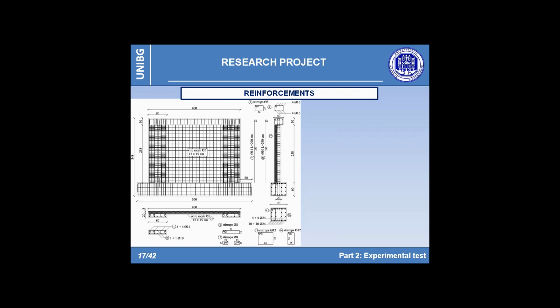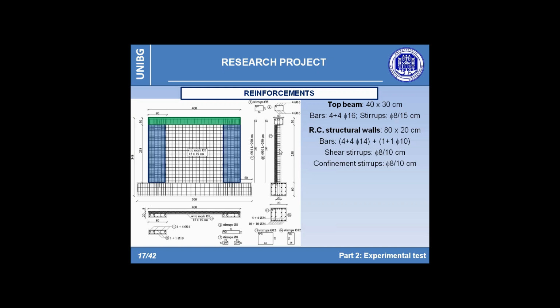In this picture, that is the last regarding the experimental campaign, the specimen geometry and the reinforcement details are shown. As you can see, the spacing of the bars and of the stirrups is very repetitive, highlighting a regular layout. In particular, you see here the reinforcement designed for the upper beam, the one related to the structural walls, and the infill panels armed only with a light 15 centimeter wire mesh with a diameter of 5 millimeters. Finally, the foundation has been designed to be over-resistant, and for this reason it was strongly armed to behave elastically.